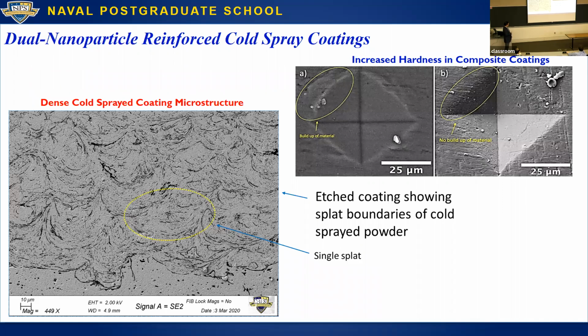These are the cold spray composite coatings. This was done using a high pressure system. This is the classical structure you get with cold spray. All of these individual features that you see here are essentially particles that have been flattened. And if you look at this indent profile here, or SEM images of it, on the left is the composite. So you can see at equivalent load, you have a smaller indent, higher hardness. But then if you look at the morphology, you actually see some pileup here, or buildup of material in the circled area. And that represents that you have some plasticity in the material, which you don't really have in the starting cold spray deposit.